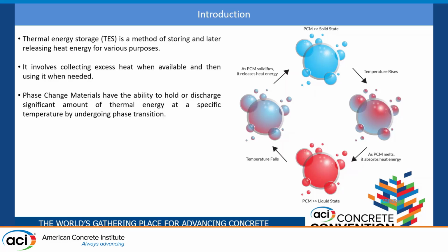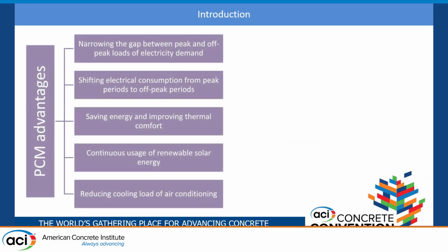When the temperature rises, the PCM melts, absorbs a significant amount of heat, and becomes liquid. When the temperature goes below the solidification temperature of the phase change material, it starts solidifying and releases the heat to the surrounding environment, which prevents an instant temperature increase or decrease. So they could be really beneficial in buildings.